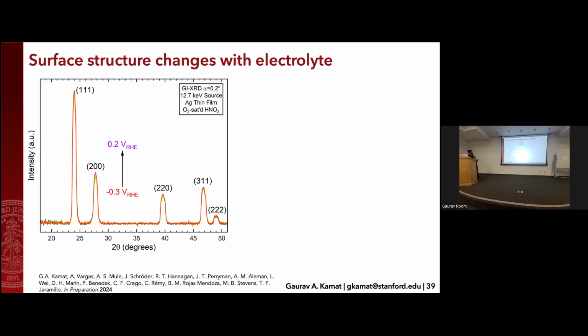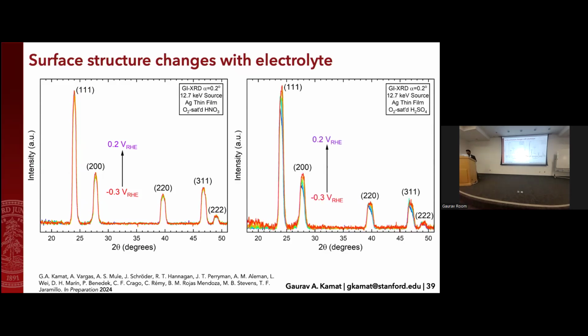Going on to nitric acid in silver. So previously it was perchloric and now nitric. We see a lot smaller magnitude of changes, although we didn't test it in as wide of a potential. And perhaps the most interesting one is this one, which is in sulfuric acid. So as you apply higher and higher potentials, you can actually see these peaks start to skew to one side. And that's evidence of local surface strain.